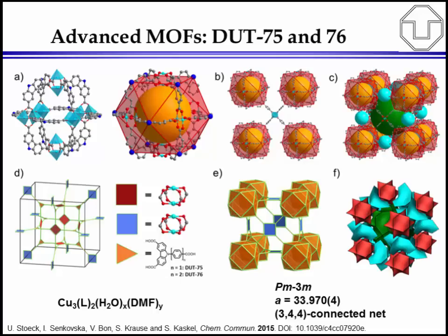So these metal organic polyhedra shown in A resemble a pore on their own. It's one pore basically and not connected yet, but we designed here a concept where the carbazole nitrogen, which is marked in blue in figure A, basically can be used to connect, via a secondary square planar node unit, these metal organic polyhedra. So you can make a porous material out of metal organic polyhedra, and this creates additional large, huge pores, and this creates a very high degree of porosity.